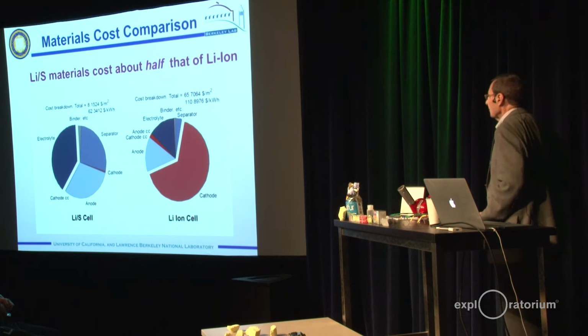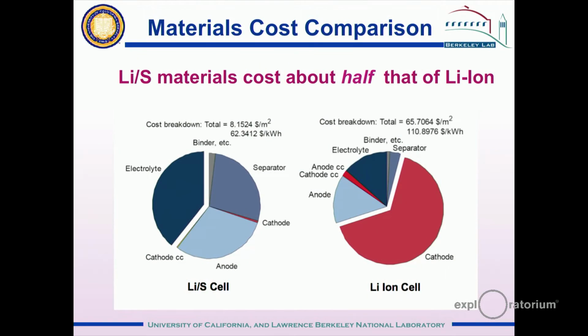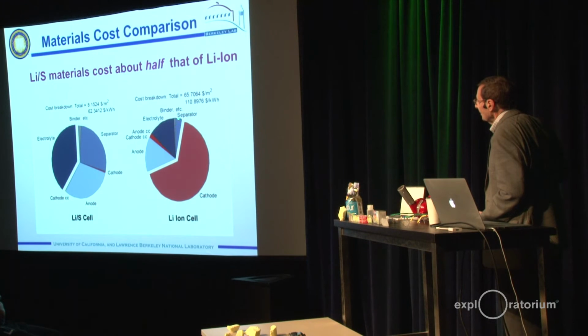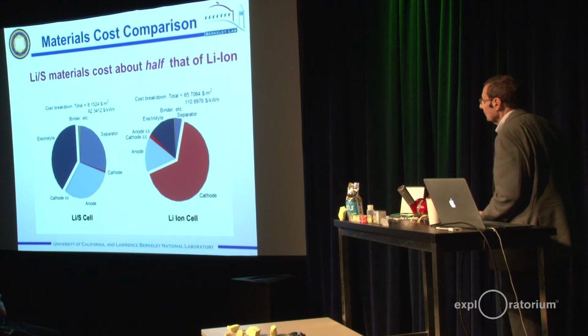We asked one of our industrial colleagues to make an estimate of the cost of the materials to make the lithium sulfur cell and compare that to the lithium ion cell. So on the left we see the breakdown of the materials cost for the lithium sulfur cell compared to the breakdown of materials cost for the lithium ion cell. You can see that in the lithium ion cell, the positive electrode is by far the largest cost item. But in the lithium sulfur cell, the positive electrode is by far the lowest cost item in the cell. The separator cost in the lithium ion cell is the same as in the lithium sulfur cell, so that allows you to see that as a percentage, the separator takes up a larger fraction of the total cost, and this is an indicator that the total materials cost for the lithium sulfur cell is much less than that for the lithium ion cell.